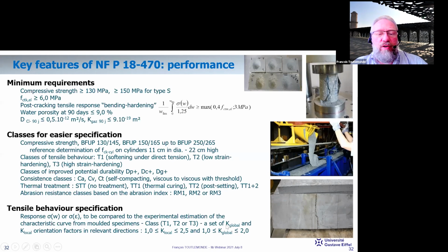A set of orientation factors is given and must be checked in the relevant directions. This orientation factor has to be between 1 and 2.5 for the local factor, and between 1 and 2 for the global factor. This may lead to reconsidering the casting method so that the orientation factor is consistent with what is necessary for the tensile force equilibrium in the project.